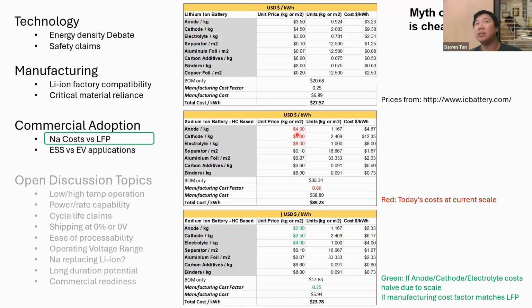Likewise, cathode, because there's no lithium in there, there's possibly no critical materials in there, it could be $2.50, considering that lithium containing LFP is $2.50. And electrolyte, half of $8 is still more than the lithium electrolyte, but just for simplicity's sake, we kept it the same. And let's assume the manufacturing cost factor for sodium ion can reach the same levels as lithium ion.